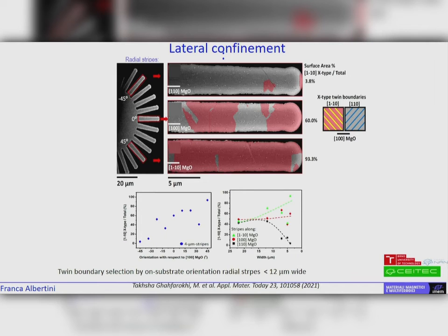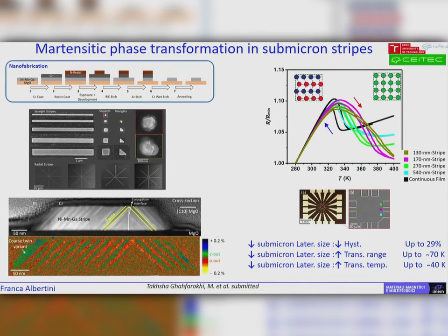And we have nicely found also a selection of the orientation of twin boundaries depending on the relative orientation of these stripes along the substrate. And we have reduced the size by electron lithography. In this case, we've seen big effects by reducing size on the Martensitic transformation. We have a reduction of hysteresis by reducing the size, but an increase of the range of the transformation. It is more broadened, and an increase of the transformation temperature.